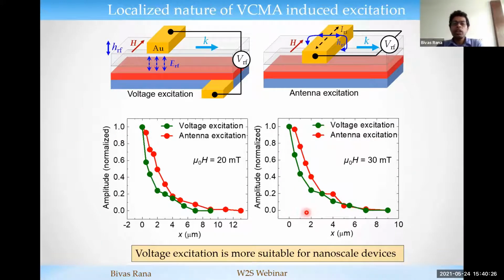One of the most important features of this VCMA, or I would say advantage, is the local excitation. As I explained, this electric field is strictly confined underneath this gate electrode because the thickness of the oxide layer is way smaller than the width of the top gate electrode. To see the localized nature of this VCMA-induced spin wave, we looked at how the amplitude of the spin wave varies as a function of the propagation distance. These blue dots show the experimental result, and it shows a nice exponential decay as a function of the propagation distance.